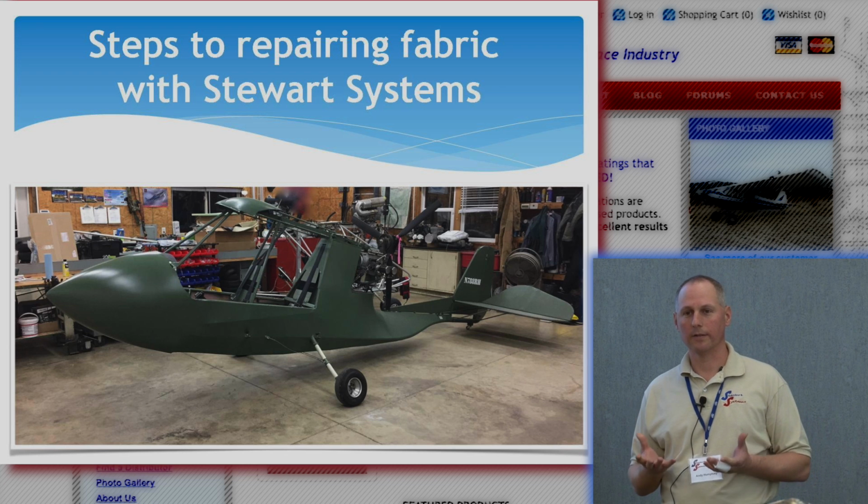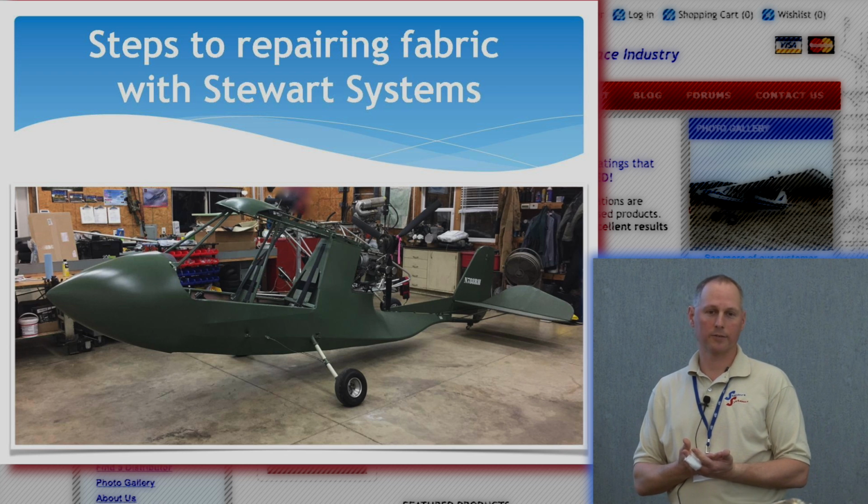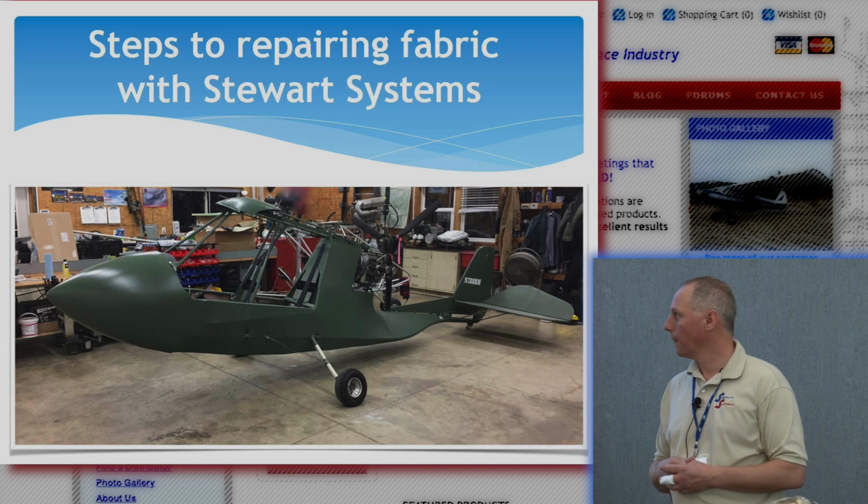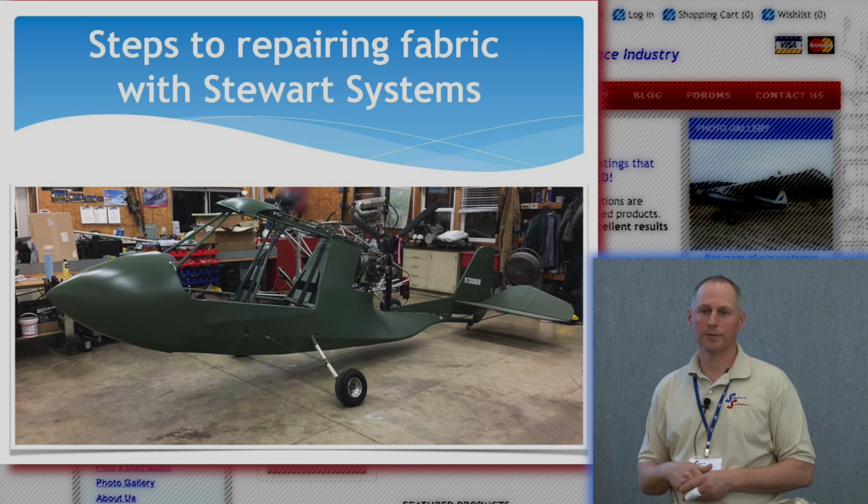It's when it gets on the back side. If you've got wing tanks, your wing tank leaks down on that Ekofill. That is going to cause a problem eventually. If you get it fixed real quick, it may not bother it at all. We had a leak in the shop one time on a Stewart Systems airplane, and it leaked for about 2 weeks. And we saw just a little bit of rippling on it. It wasn't a big deal. That was with autogas.